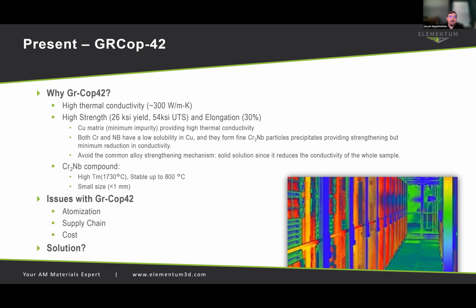And so as you're at these very high superheat temperatures to dissolve those chromium compounds, you end up having that kind of race. Do you dissolve your crucible faster and therefore have contamination from the crucible, or even bigger problems than that, before you're able to atomize all of the material, which then limits the size that you can do at one time. So I think there's a lot of challenges with that. There are a lot of great companies doing atomization of these materials and getting better at this and finding new crucible materials and different ways of doing it. But it is still limited, and the volume of powder that's possible to produce is really limited by some technical concerns, not just the commercial concerns of making GRCOP 42.